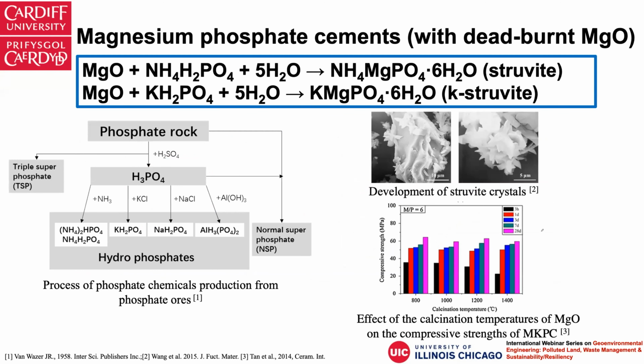And the next cement I'm going to talk about is called the magnesium phosphate cements. So this cement is based on the acid-base reaction between a magnesium oxide and a phosphate source. In cement and concrete studies, people usually use dead burn magnesia. If you still recall what dead burn magnesia means, it is the magnesia that has been calcined at the highest temperature in order to give it a very low reactivity.